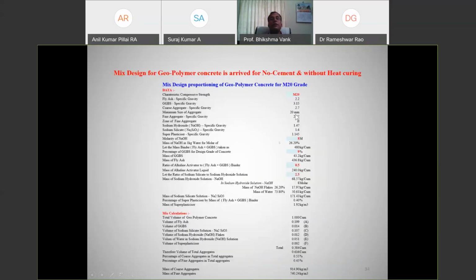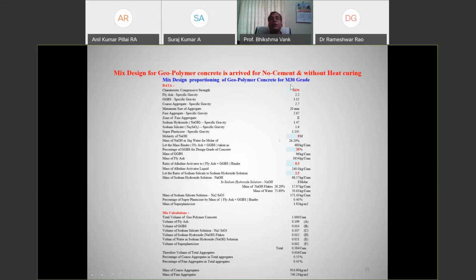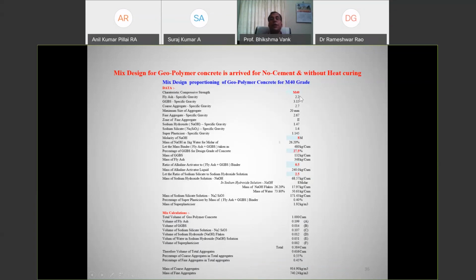These are the trial mixes that are being given. The mix design for geopolymer concrete is arrived at with no cement and without heat curing, ambient curing, for M20. This is the mix design done for M20. And this is for M30. This is for M40. This is for M50. And this is for M60.